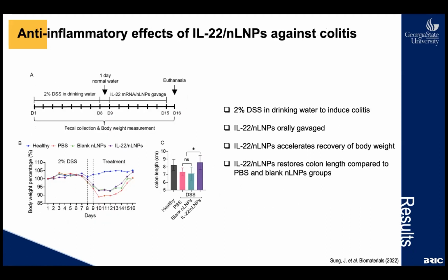Now we tested on the ulcerative colitis mouse model to observe the anti-inflammatory effect of the IL-22 lipid nanoparticles. 4 groups of mice containing 5 mice per group were treated with or without the IL-22 lipid nanoparticles, and colitis was induced by 2% DSS in water for 7 days, and treatment was only orally administered for another 7 days. Mice were euthanized 1 day post-treatment.